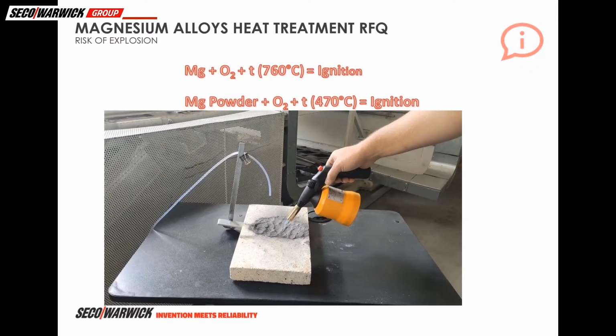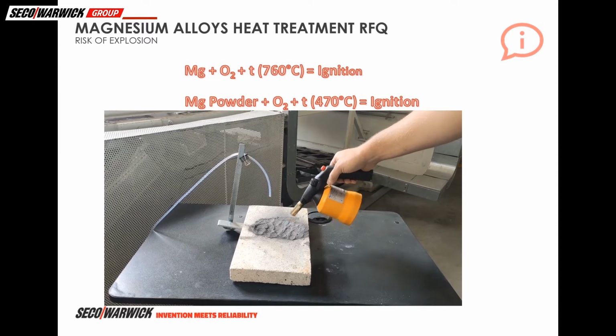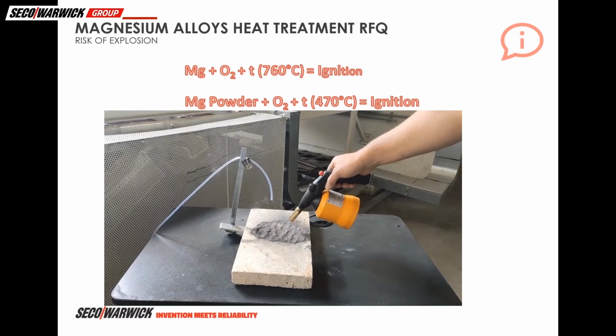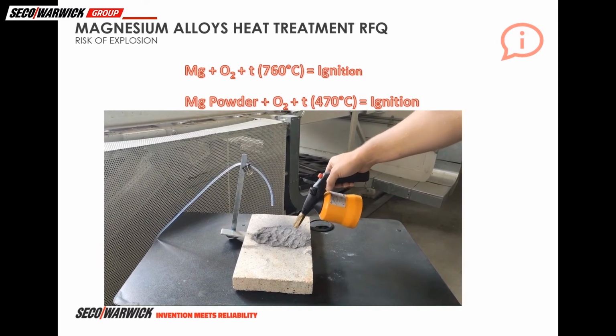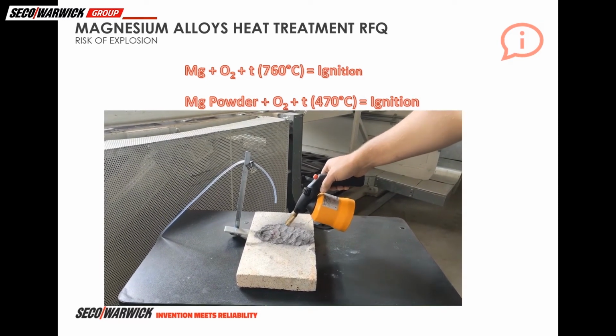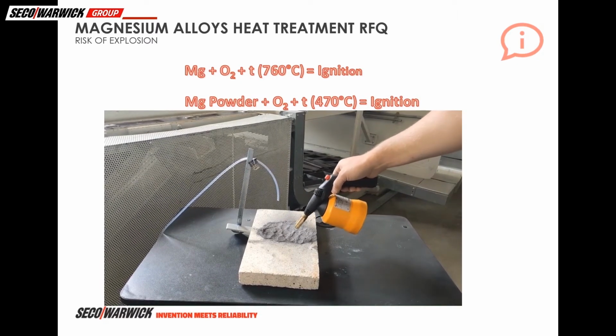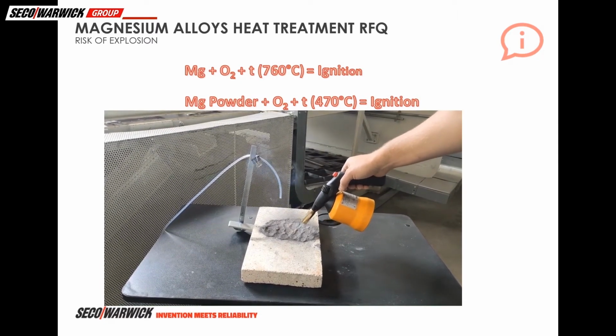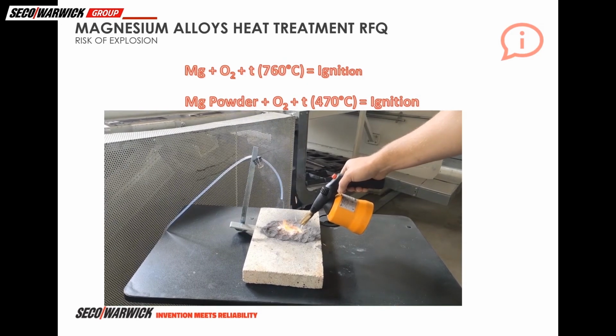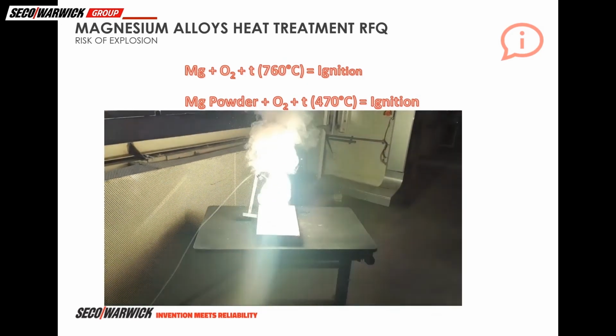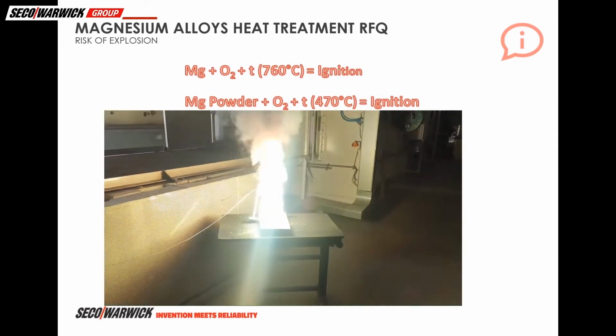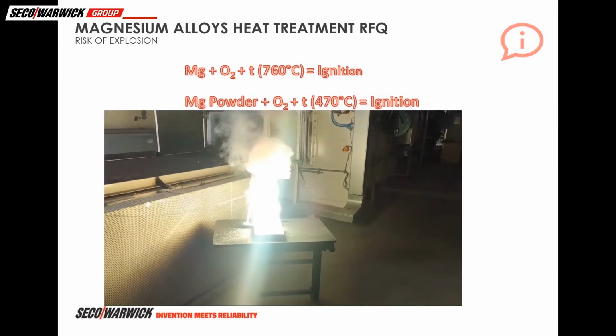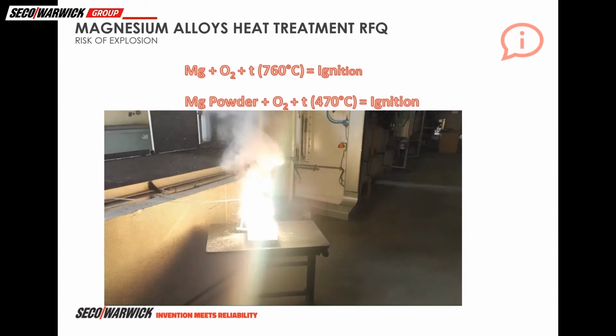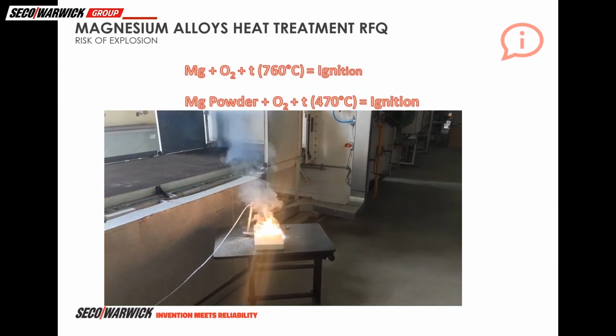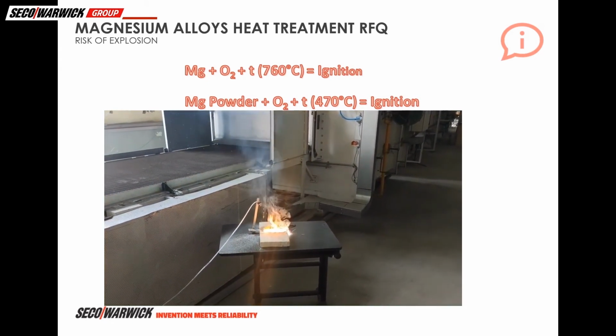But with so far unknown to us magnesium alloys, additional questions arose. In industrial conditions, heat treatment of magnesium alloys is associated with the risk of explosion. Under the influence of temperature and presence of oxygen, easily flammable mixture is formed. Clean magnesium starts to burn at a temperature of 760 degrees and magnesium powder even at a temperature about 470 C. However, our experience shows that magnesium alloy can start burn at lower temperatures. This movie shows you how the chemical reaction of magnesium ignition occurs under mentioned conditions. The presence of high temperature and oxygen.